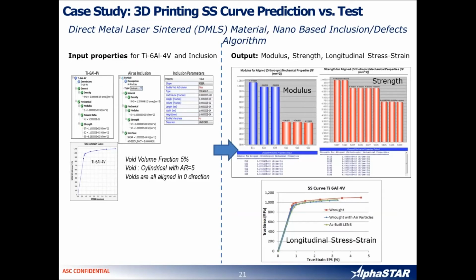Okay, another case study that I'm going to show you for the metal AM process, the 3D printing stress strain curve prediction versus test for titanium aluminum alloy. So we use a direct metal laser sintering material, and then we use a nano-based inclusion defect algorithm to predict the stress strain curves with and without the inclusion. For example, on the left-hand side, you see the titanium aluminum alloy material properties with air as inclusion, modeled as cylinders, and also we introduce the stress strain curve of the basic titanium aluminum alloy. On the right, the output that we get is modulus, strength, and longitudinal stress strain curve, and it's compared with